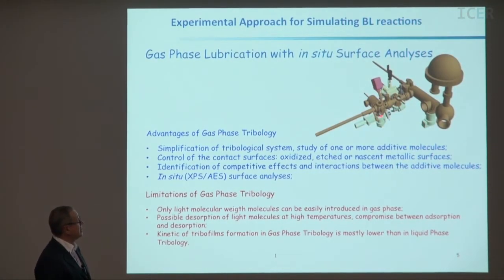This means that we are typically in a hard working condition. So the tribometer is in this part here, and after the test, we have to transfer to the analytical chamber here. So the advantage of this method is to simplify the tribological system, because in presence of gas, you have no hydrodynamic lubrication. But you can introduce several gases, so to study the mixture of molecules. You can control the contact surface, remove the oxide, clean, remove the contamination. And you can, of course, analyze the surface.